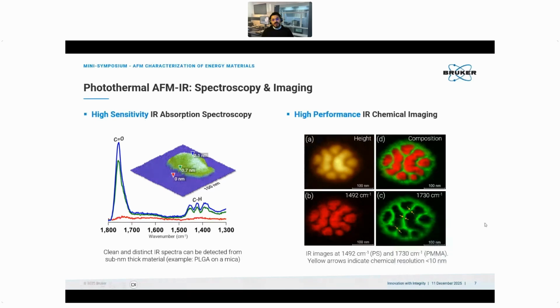Well, I have turned my Teams off, but still popping out messages. Anyway, sorry for that. So we will be imaging only where the absorption happens of that wave number. So we will have a map of absorption. For example, on that structure, if we have sent the wave number of the laser pulse at 1492 centimeter minus 1, which is the one corresponding to an absorption for polystyrene, and then we start mapping, imaging in topography, parallel to the topography at the same time. It's based on lock-in techniques. And then we basically see that those areas of the sample are the ones that have high absorption, while the rest is not absorbing. So we would know then that these areas basically must contain polystyrene.